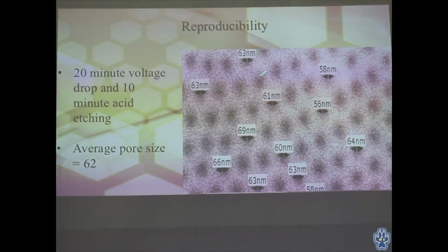This is just a slide to show an example of the reproducibility of these samples. So we created another one doing another 20-minute voltage drop and a 10-minute acid etching, and the pore size is on average 62 nanometers again.